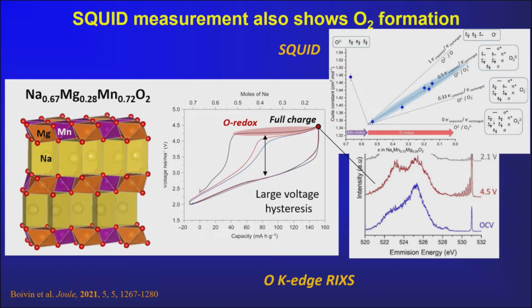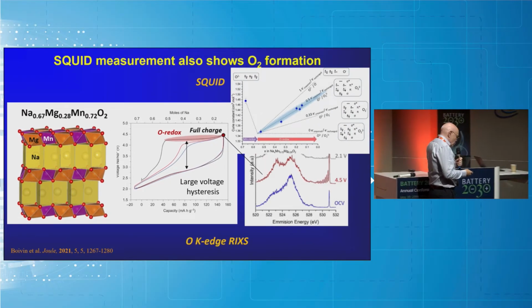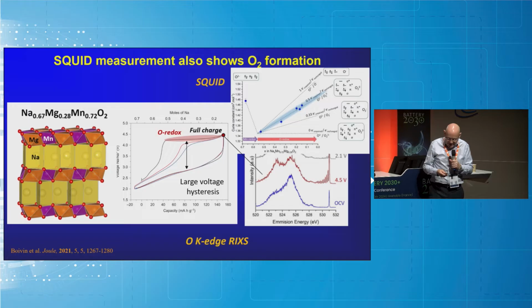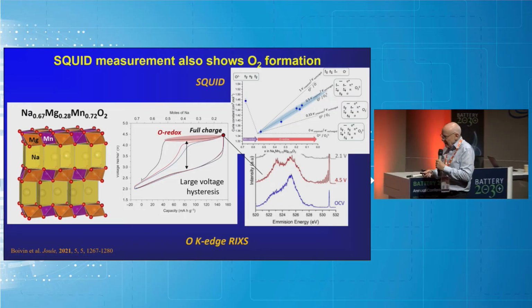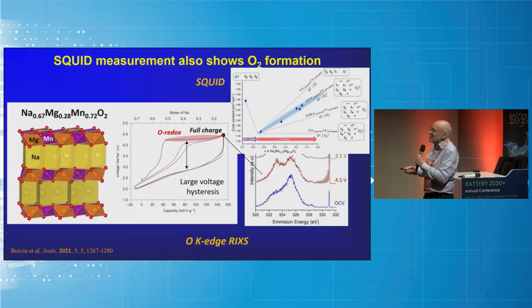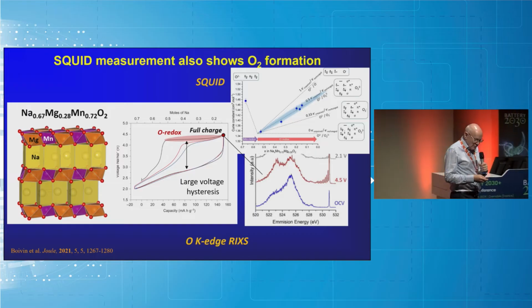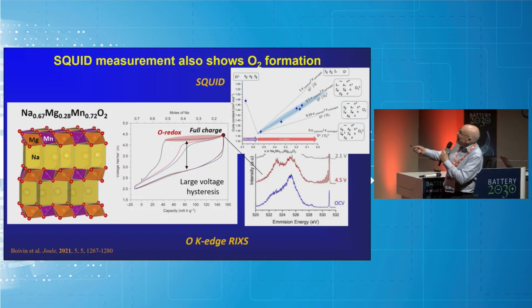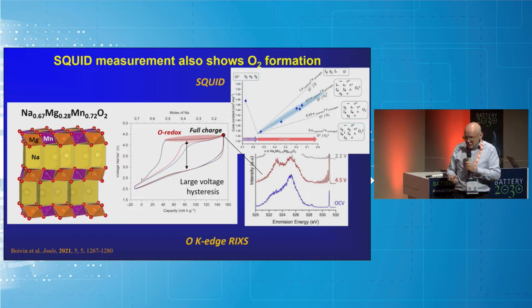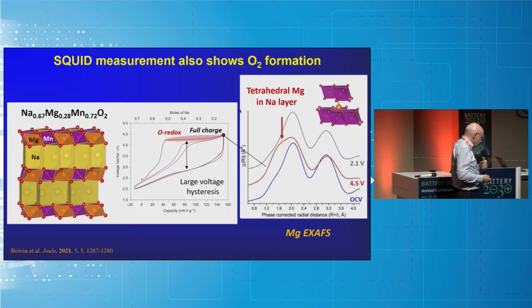Now, what you see here is the change in the Curie constant sits on this line, which is the formation of molecular oxygen. Of course, every oxygen has got two unpaired spins. And so you can use magnetism to probe this process. Magnetism is non-destructive, non-invasive, samples the whole material equally, and there again you see evidence of O2 formation.